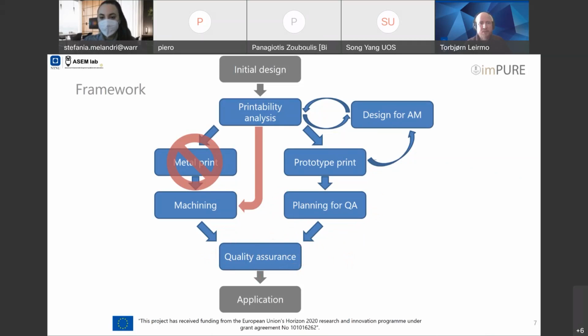And then in between, you also have the possibility that additive manufacturing gives extra value, but it is also too time-consuming to print the entire part. This leads to this hybrid solution where you can do some metal printing and machining and do this in tandem, or going back and forth really from metal printing and machining. For powder bed fusion, this is not really a good solution, technically speaking, for traditional work, but we have actually done this in our lab where we had some issues with the print. We removed the part from the print build chamber, removed all the powder, did some machining to the part, and reintroduced the part into the build chamber to finish it off.